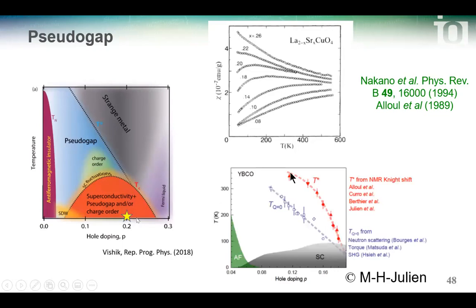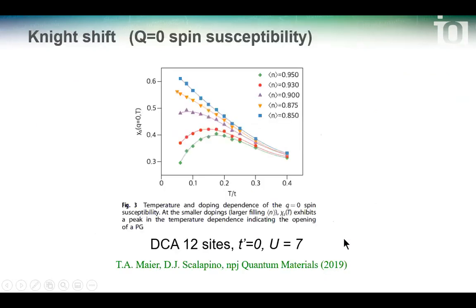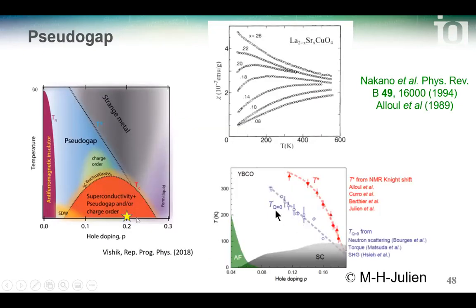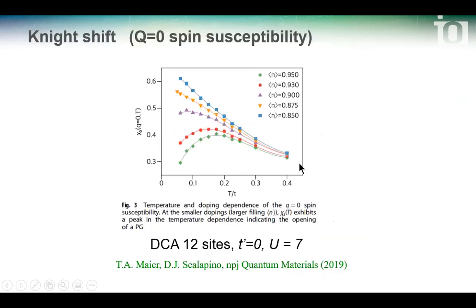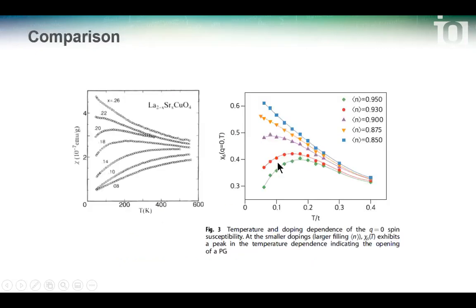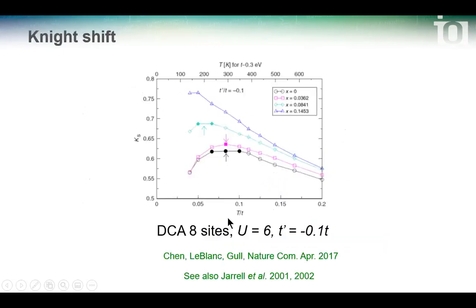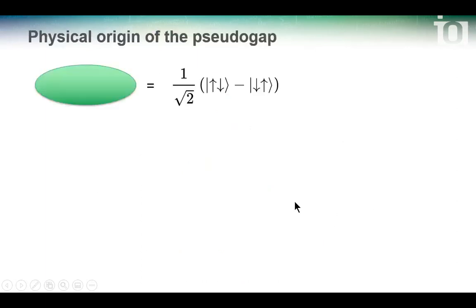And this loss of density of states occurs along this red line that is slightly above another line where phase transitions occur. So this is what happens with DCA 12 sites, and you can see that it has the same shape as the experiment. If you look in detail, the doping does not quite correspond. I mean, this is electron filling and hole doping, but this is again an effect of the 3-band model. The point is that you have the same behavior with a maximum here, and then at large doping, it goes like that. So 6 sites gives the same, and 4 sites gives the same.